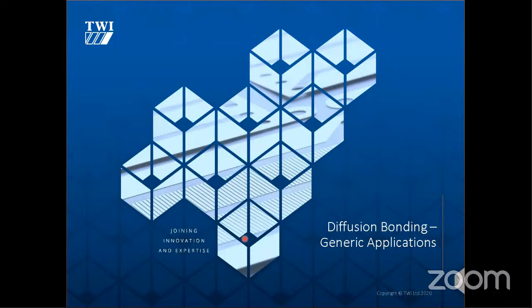But typically speaking, if you're doing a solid state generic diffusion bond, you want your surface roughness to be sub-micron. So I like to go for 0.4 micron RA or better. And with the flatness, again, you want it very, very flat. So you're talking, if you're aware of optical flat measurements, there's something called light bands, and we like to go for better than 4 or 5 light bands of flatness, generally speaking.